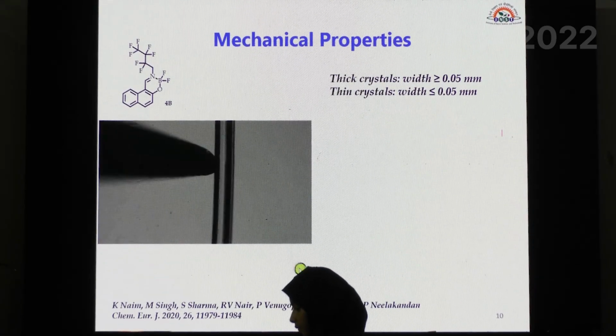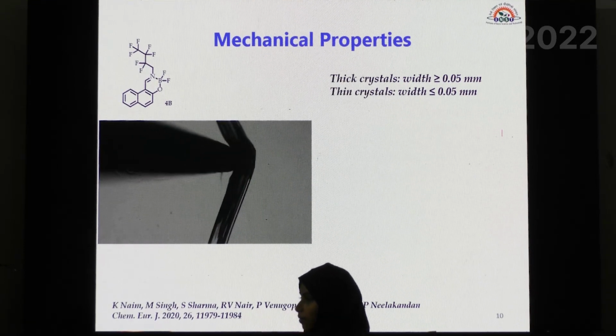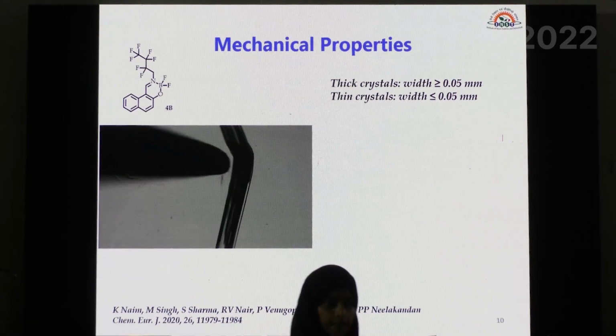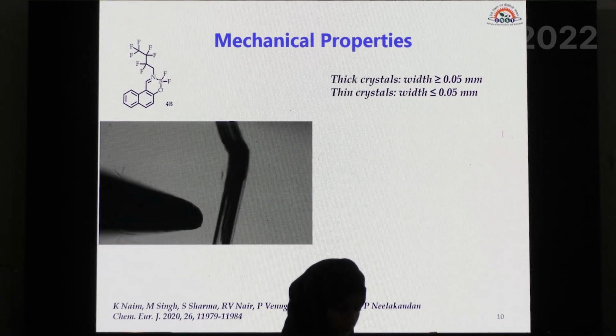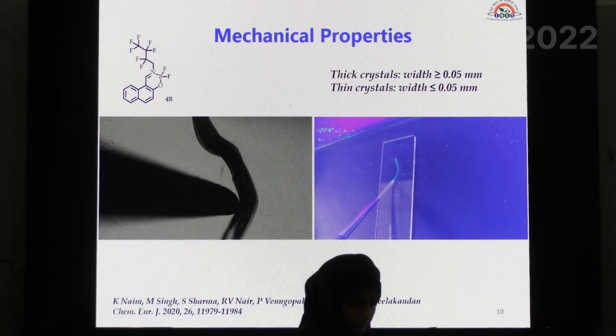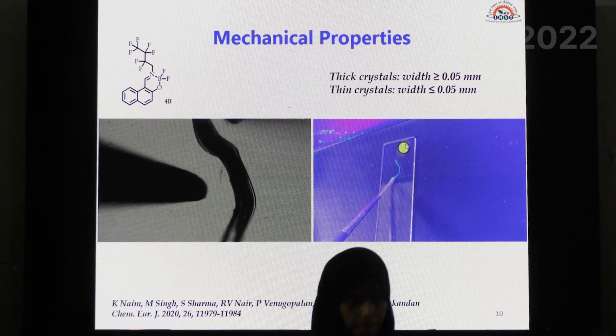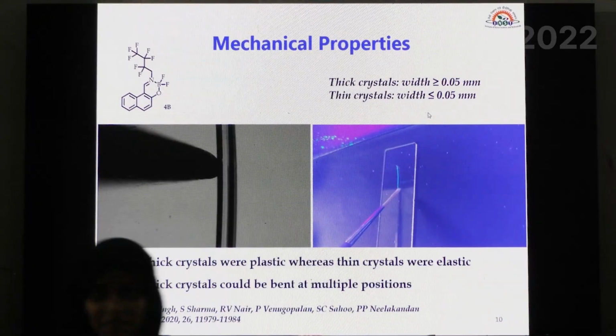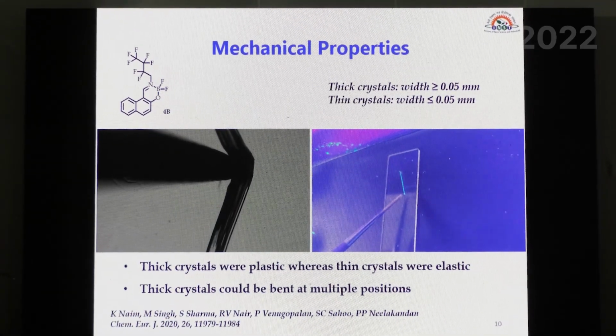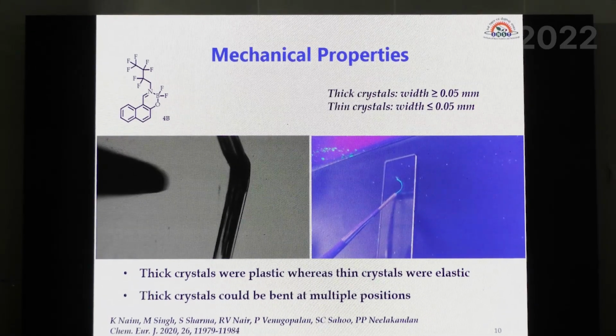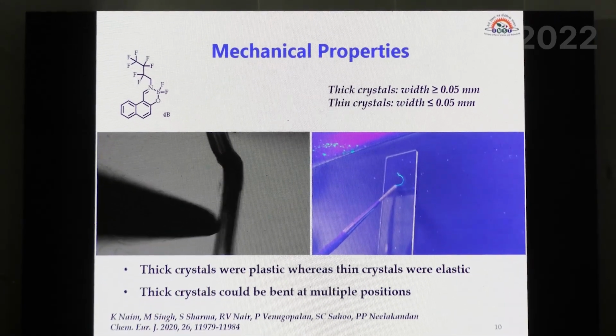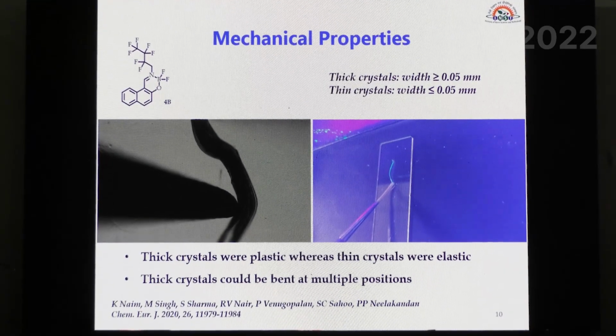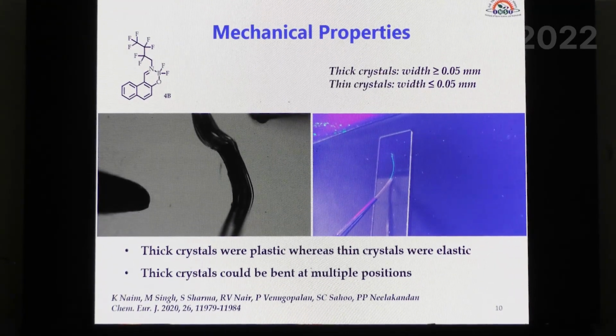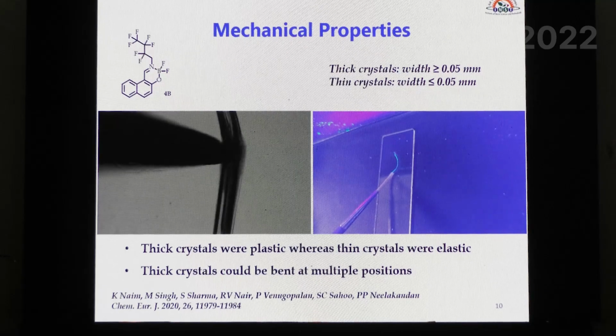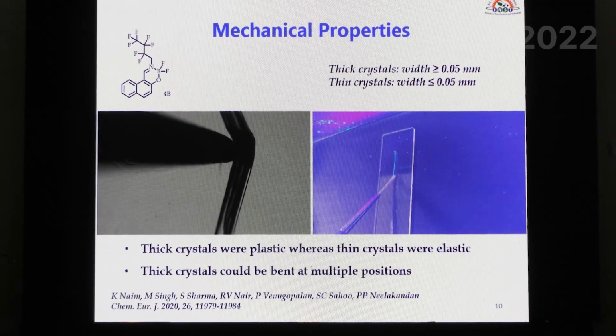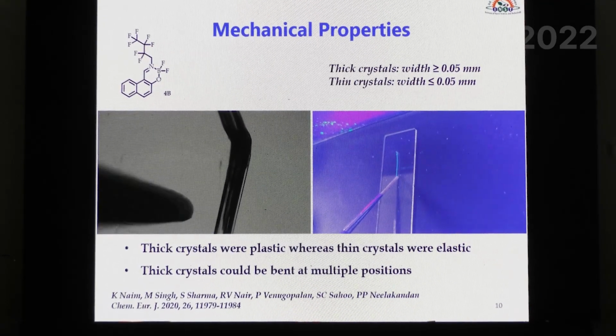This is again a crystal, and this is the tip of a forceps. We are pushing it in one direction, and you can see that it retains that shape. But on the other side, this is the other crystal, which is very thin, having a width less than 0.05 mm. When you push it, it bends, it will not break, and if you take out the stress, it will come back to the original state. And this you can do multiple number of times, and unless you apply a very high stress, it will not break.